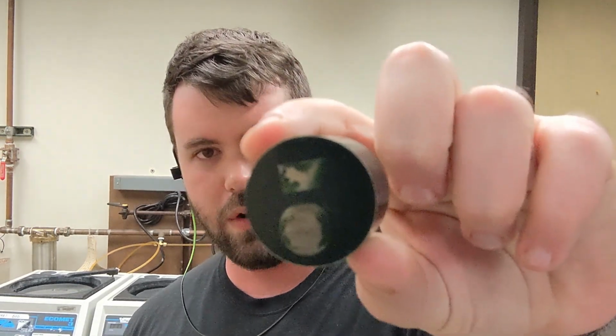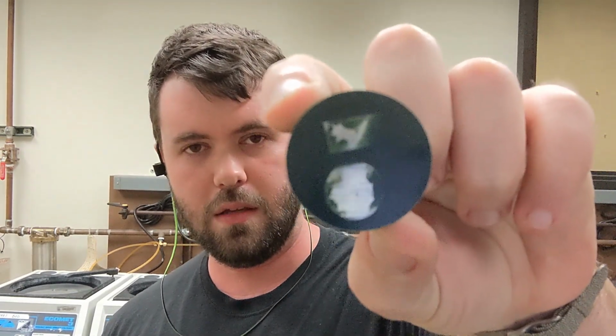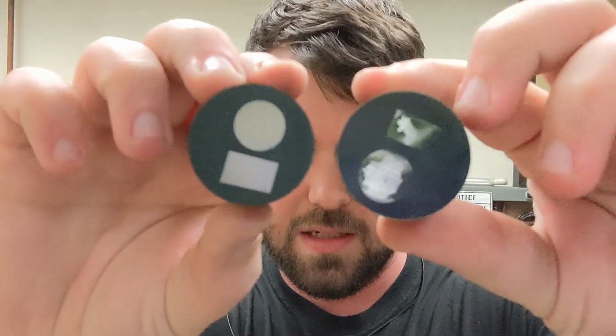So I've finished the 600 grit polishing step for one of our samples, and just for comparison to see the progression of polishing, this is how our sample looks initially when it comes out of the phenolic resin press, and after 3 passes on the machines, we turn into this.